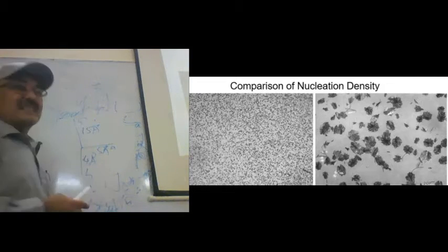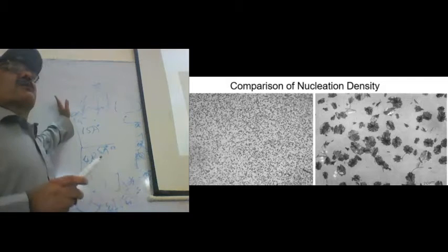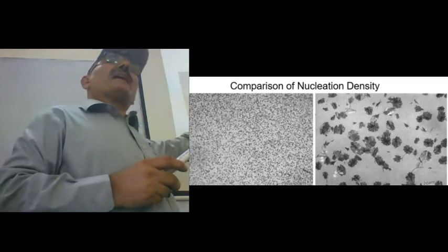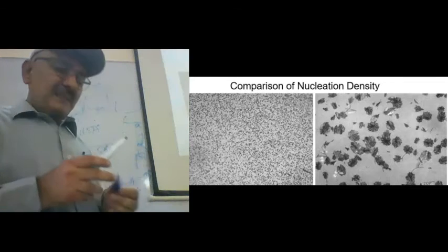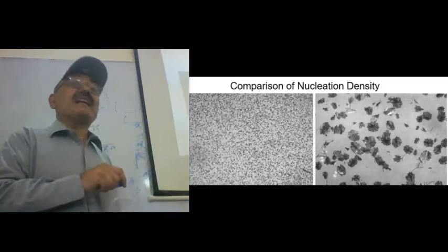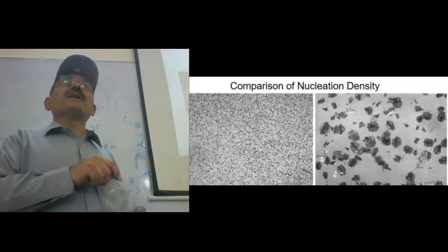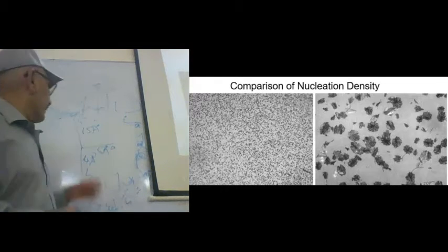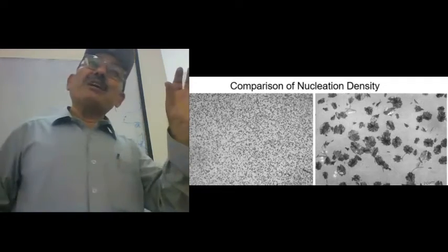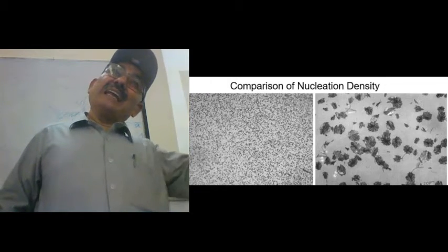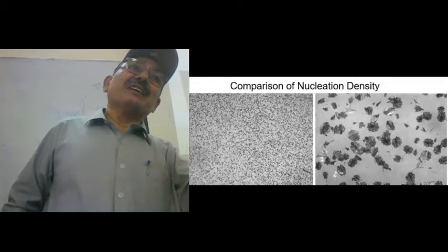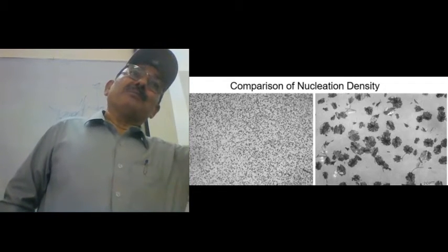Then common sense says that this crystal will grow more in this direction, because the addition of a single plane increases the dimension by 15 angstrom in comparison to the other. But no, this is not true in many cases. The direction along which a plane can be added requiring less energy will preferably form.